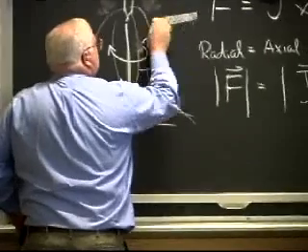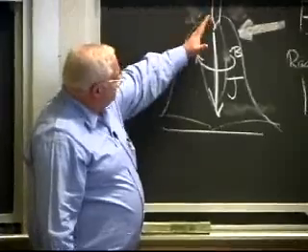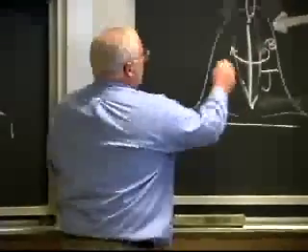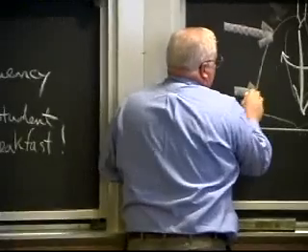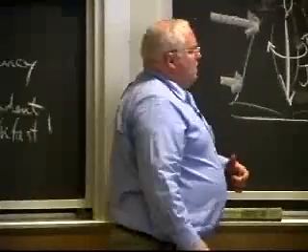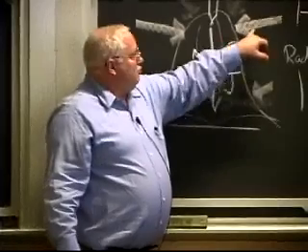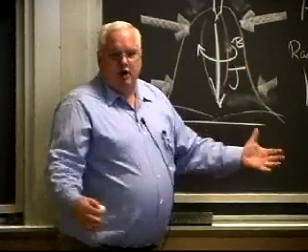And it turns out, where's the current density the highest? If I have constant current flowing through this thing and the current is diverging, obviously the highest J is up here where the area is smallest, right? So I have big forces up here. I have small forces down here, smaller forces. They're all directed radially inward. Well, if I have a radially inward directed force, that's nothing more than a pressure, right? And if the pressure is high here and low here, that's a pressure gradient. And if I have a fluid and a pressure gradient, what happens?